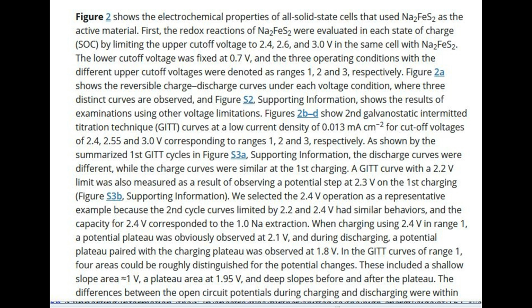We selected the 2.4 V operation as a representative example because the second cycle curves limited by 2.2 and 2.4 V had similar behaviors, and the capacity for 2.4 V corresponded to the 1.0 Na extraction. When charging using 2.4 V in range 1, a potential plateau was obviously observed at 2.1 V, and during discharging, a potential plateau paired with the charging plateau was observed at 1.8 V.